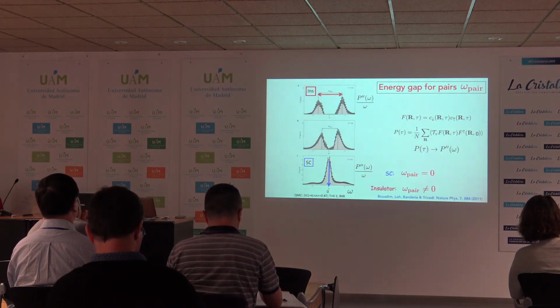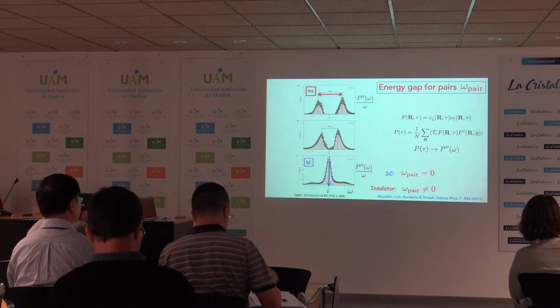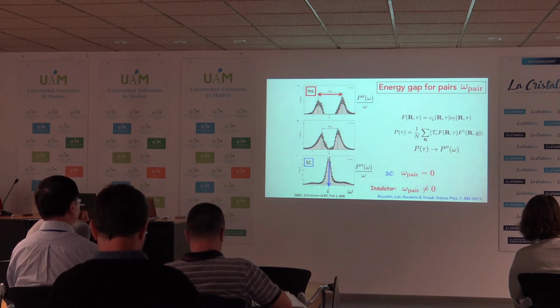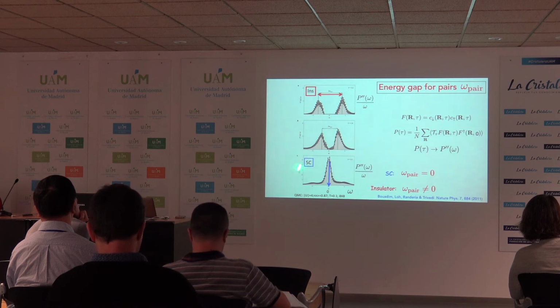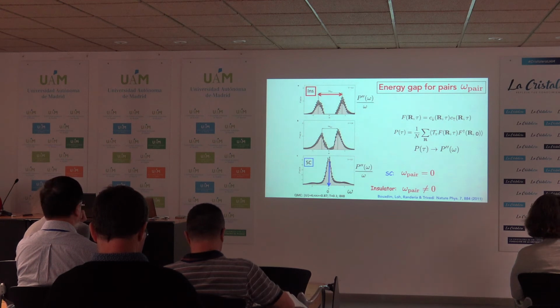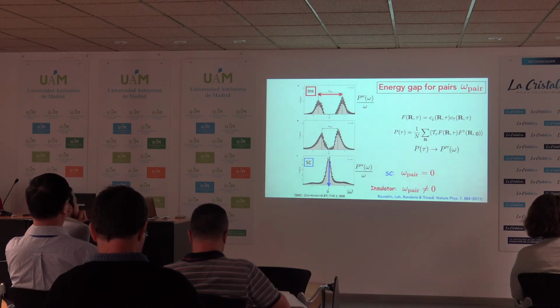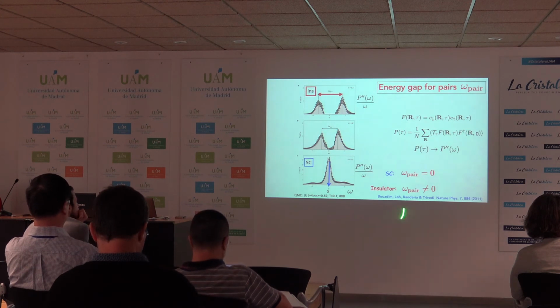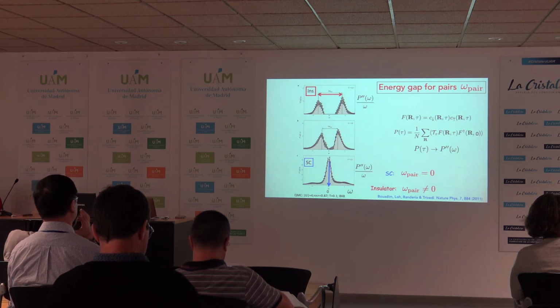Okay, this is now back to our quantum Monte Carlo results, showing now the energy scale. I want to come back to that. What is the energy scale that goes soft? This energy scale can be obtained now from P of omega. So, Erman, your question: if you now average over the whole system and just do a tunneling spectroscopy with a superconducting tip, let's say, then you would see on the superconducting side at zero energy or zero voltage, you can insert Cooper pairs. But as you enter the insulator, that peak will split, and the energy scale of that splitting is something you can calculate or measure.